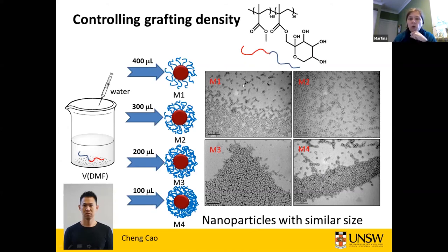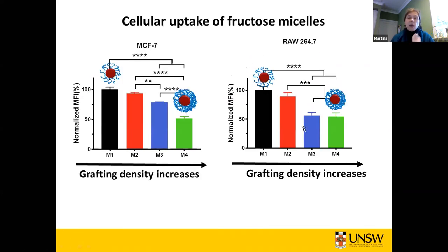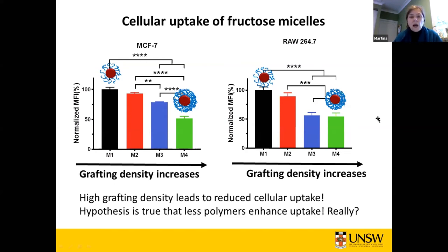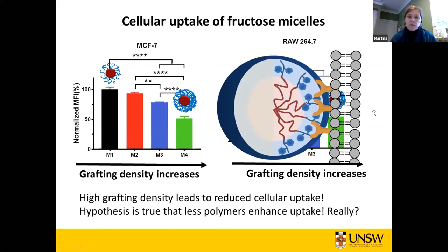So according to our hypothesis, M1 should have the best cellular uptake. And so we did that. We incubated that with a few different cell lines, and we did find it had indeed the best cellular uptake here. And the higher the grafting density was, the more it goes down. And sort of our model, where we said our polymers here on the surface need room to move around and to interact with the receptor, that should have really worked well.